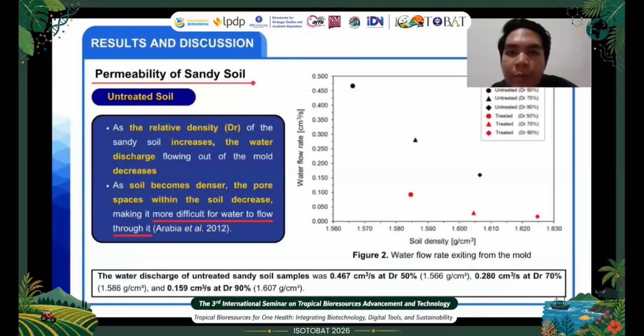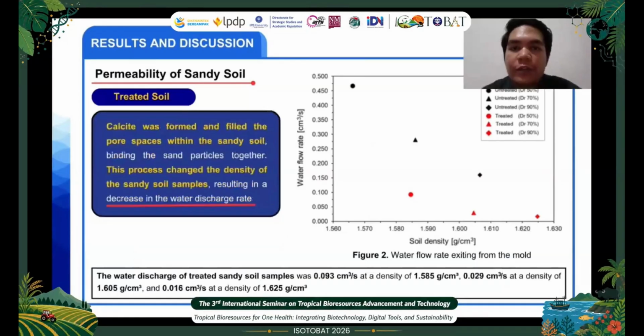Based on the results of permeability tests, the water flow rate discharged from the testing mold exhibits varying values for each level of relative density of the sandy soil. Under untreated conditions, the water flow rate decreased with each increase in the relative density of the sandy soil. As soil becomes denser, the pore space within the soil decreases, making it more difficult for water to flow through it. After treatment with the MICP solution, the water flow rate discharged from the mold after passing through the sandy soil sample showed a significant reduction. This is because calcite precipitates within the pore space, binding the sand particles together and increasing the soil density, which ultimately reduces the water discharge rate.